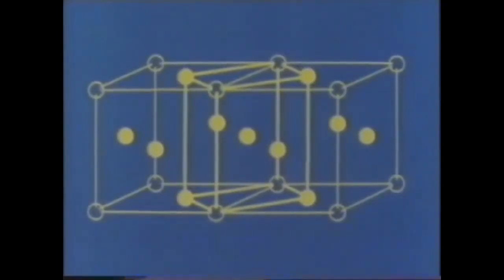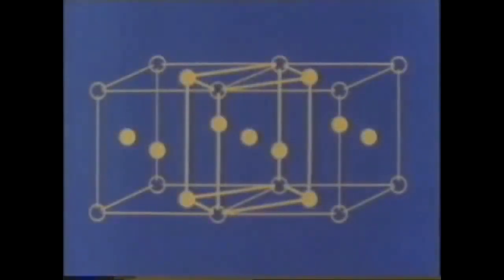It is this distortion that gives rise to the hardness and brittleness. Under the microscope, it looks like this, with its characteristic needle-shaped crystals. In practice, few steels are used in this extremely hard and brittle martensitic condition, and the reheating of the rod again to a lower temperature, tempering, removes some of the brittleness, yet retains much of the hardness. What's happened in the tempering process is that a small amount of carbon from the distorted arrangement has been allowed to come out of the solid solution.